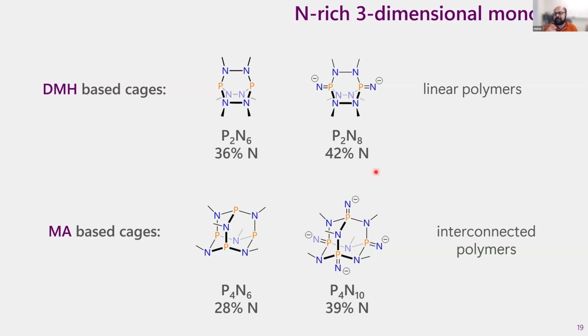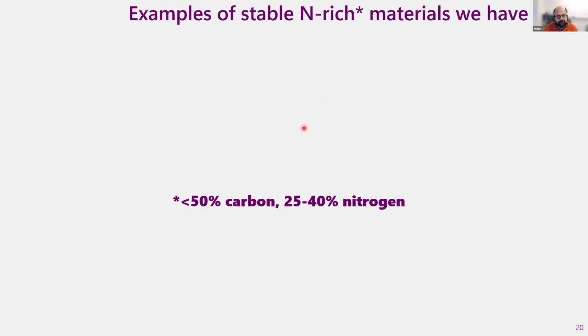And that is the dimensionality effect, going from one dimension to three-dimensional. The way we make these cages is by taking nitrogen-containing units and stapling them together in a three-dimensional shape using phosphorus. This is another atom, an element from the periodic table. So don't worry about the structures. Just know that this is what they look like in case there are some chemists in the audience. So can we build stuff from them? Yes, we can. And I'm going to show you some examples of nitrogen-rich materials that are perfectly stable. By nitrogen-rich, I mean they are less than 50% carbon. For comparison, most commercial polymers are anywhere from 70 to 80% carbon. Ours are less than 50%. The rest is nitrogen predominantly.